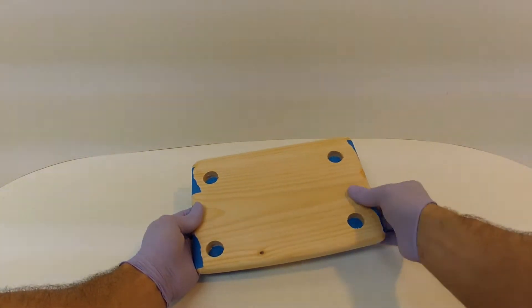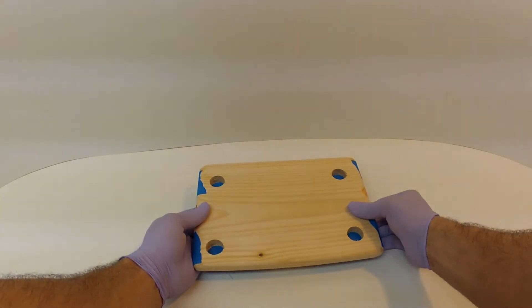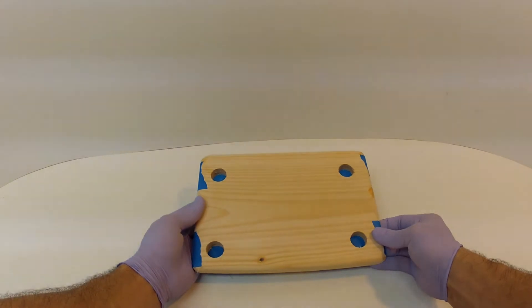You drill through the solid epoxy that way your wood on the inside is not going to get soaked with water, which will lead to delamination problems.